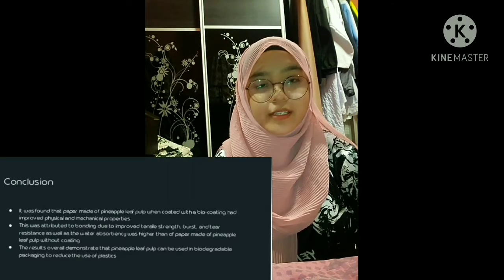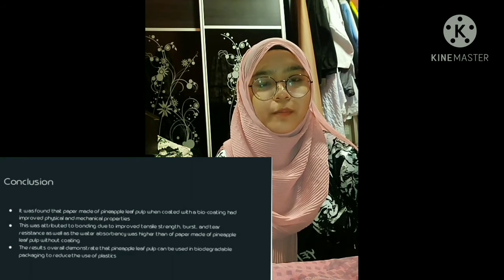The conclusion of the journal is it was found that paper made of pineapple leaf pulp when coated with a biocoating had improved physical and mechanical properties. This was attributed to bonding due to improved tensile strength, burst, and tear resistance, as well as water absorbency, which was higher than paper made of pineapple leaf pulp without coating. The results overall demonstrated that pineapple leaf pulp can be used in biodegradable packaging to reduce the use of plastic.